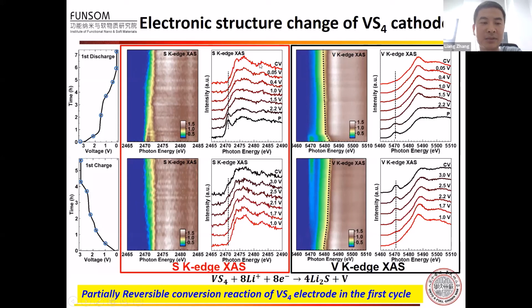And at the end of the discharge process, the spectrum is very similar to that of lithium sulfide, indicating the conversion from VS4 to lithium sulfide. And during the following charge process, the main feature is partially recovered, indicating the partial reversibility of the conversion reaction. This is also confirmed by the vanadium K-edge results.